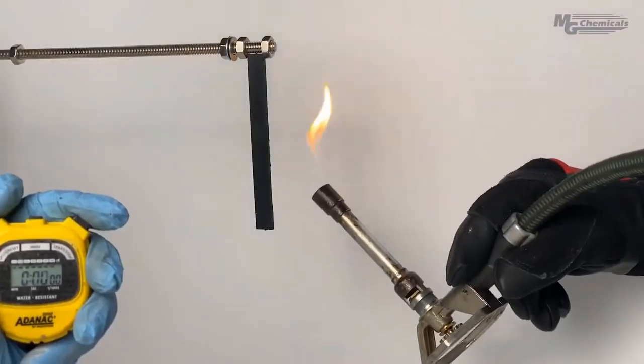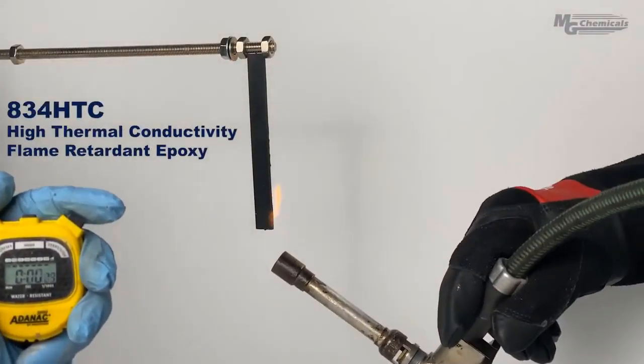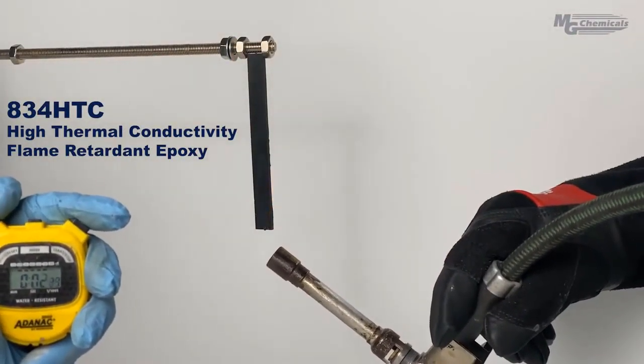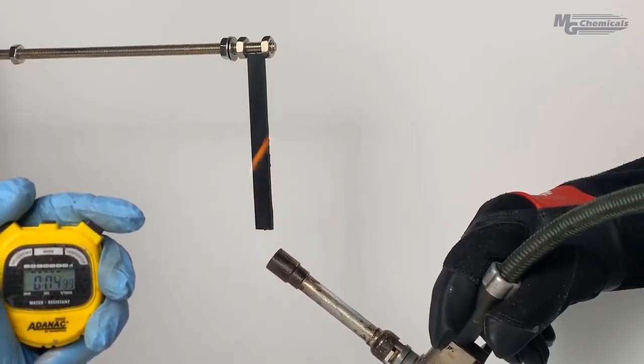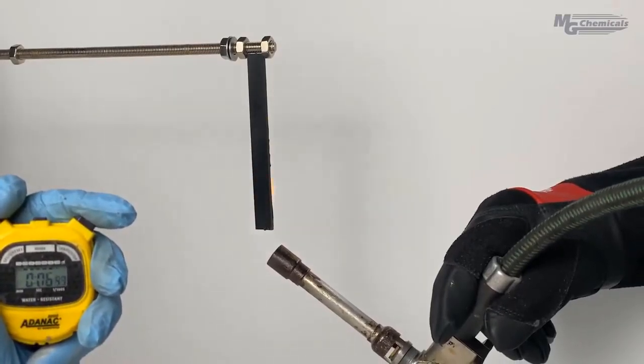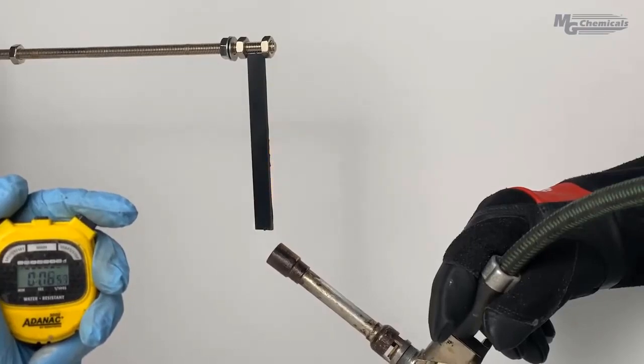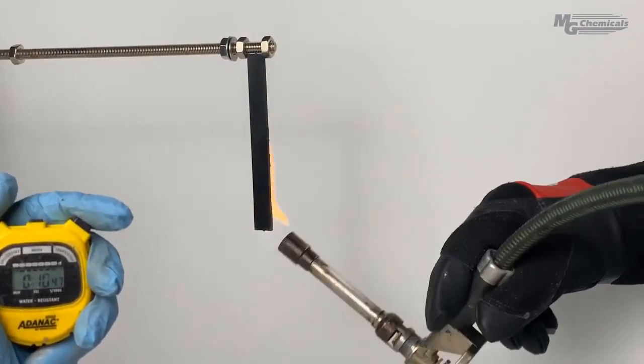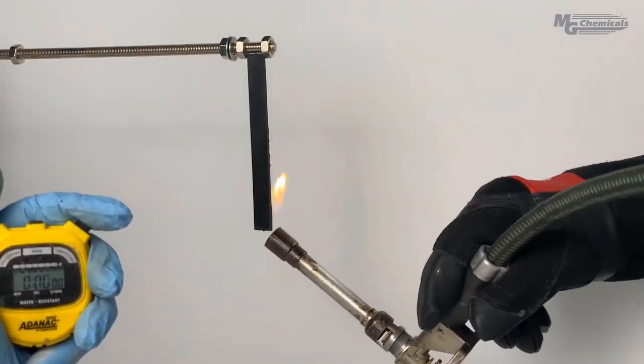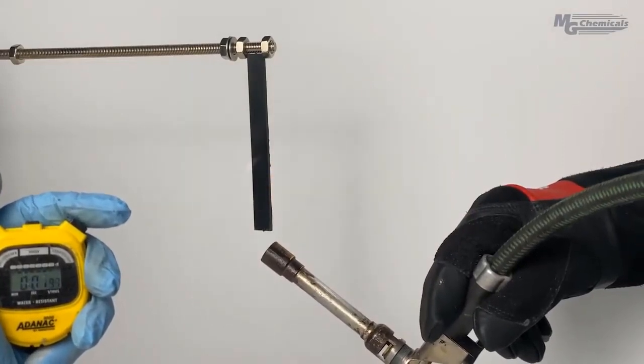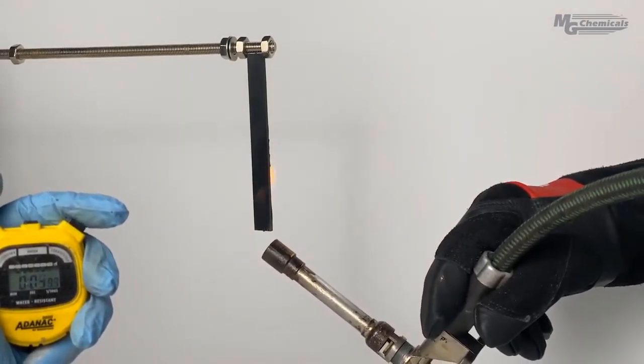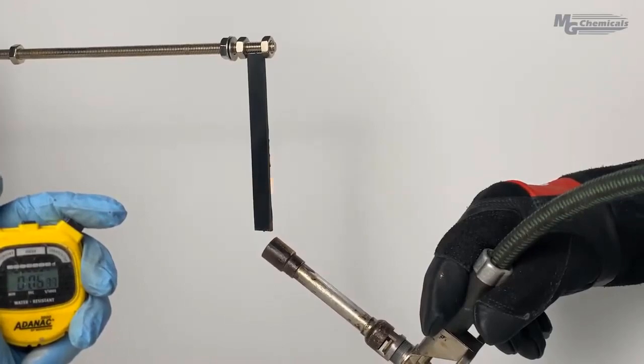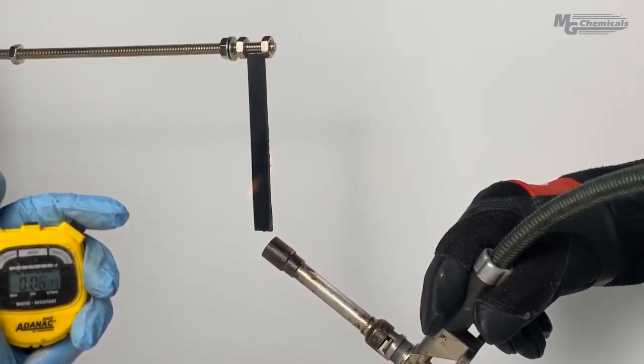Now, let's try the same test with 834 HTC, a UL-certified flame retardant epoxy. We introduce the flame for 10 seconds, then remove and wait for the flame to extinguish. Once extinguished, we repeat for another 10 seconds. As you can see, the flame does not spread in this sample and quickly extinguishes once removed.